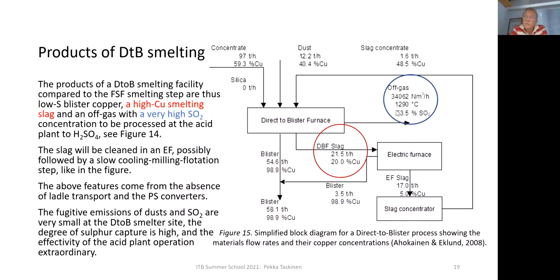We have off gas containing more than 30% SO2 going to the acid plant, and then only 1.6 tons of slag concentrate coming back from the concentrator to the smelting step, where the feed is almost 100 tons. So this circulating load within the smelter due to dissolved copper is not substantial. Dust is much more. It's more than fivefold compared to that.